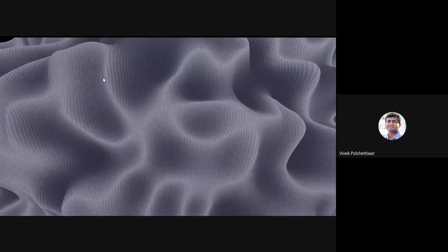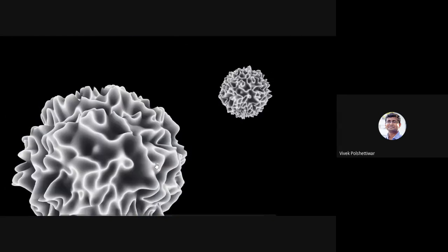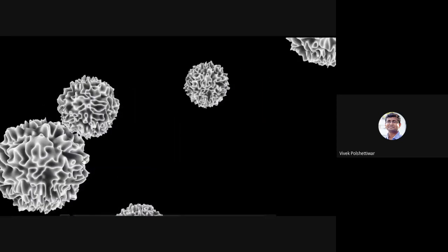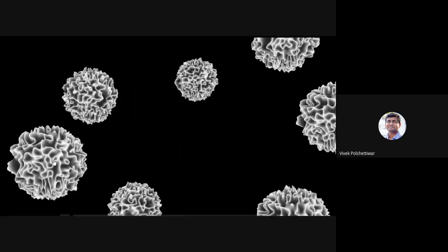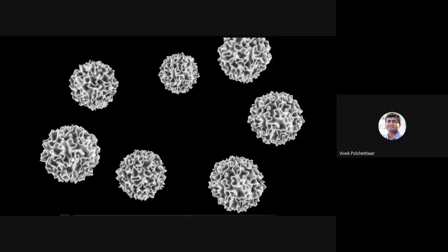And what we observe is that these are not floating flat in the solvent, but they are in the form of microemulsion droplets. And these droplets are the template molecules, or the reactors, you can say, which are made up of water, xylene, and that CTAB molecule. These are not a nanoparticle as such. These are the reactors where I can grow the nanoparticles. And in these channels, I can grow the silica.